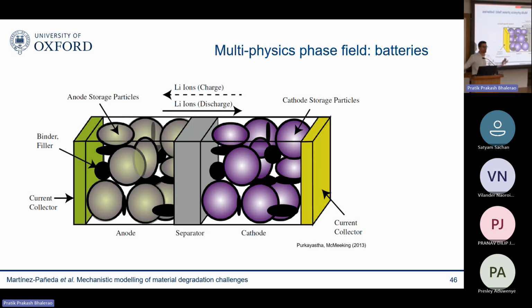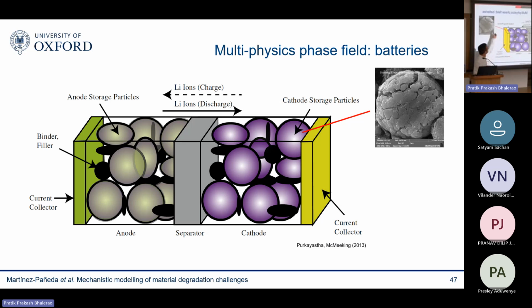And every time you charge or discharge your battery, those lithium ions are stored in these anode and cathode particles, and this lithiation process causes some deformations. You have swelling and shrinking of those particles with every charge and discharge. And that continuous swelling and shrinking leads to cracks, and this is the main degradation mechanism in lithium-ion batteries. This is the reason why you need to replace your laptop or your phone every 2 years or so.